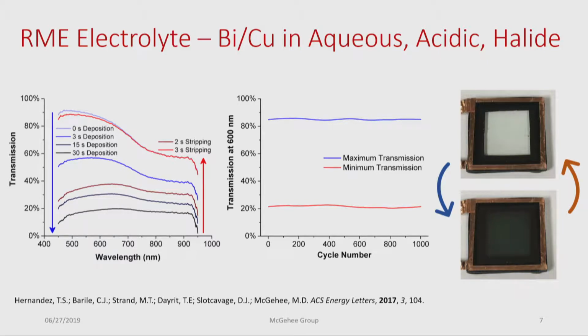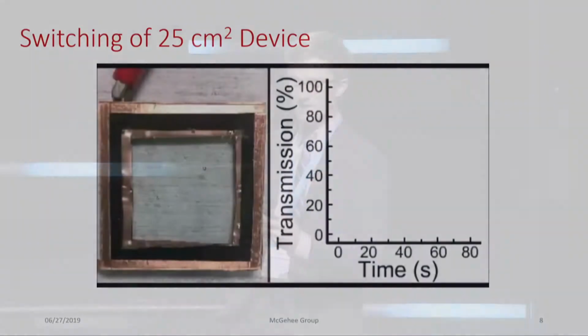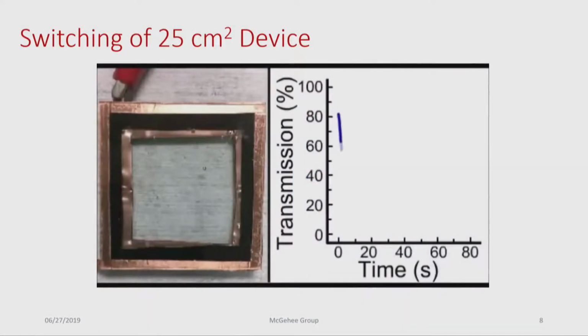So we're able to achieve a color-neutral tinting across the entire visible spectrum within 30 seconds and switch back to its initial transparency in less than 5 seconds. And we're able to do this cycling over hundreds of times. Now, I can talk your ears off all day and really nerd out about this, but I always felt that a video does more justice than words. So here we have a video of one of our initial prototypes switching at an accelerated rate. I'll let you take a look at this.